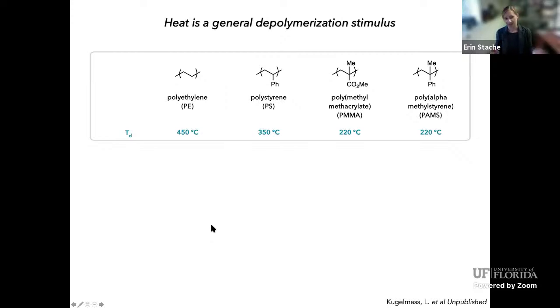Heat is a general depolymerization stimulus. And so we all know that polymers are susceptible to thermal degradation. When we think about thermal degradation, we think about kinetics, we think about thermodynamics. We look at some of our commodity polymers here: polyethylene, polystyrene, PMMA, and poly-alpha-methylstyrene, which we kind of use as a reference polymer in our lab. So kinetically, these polymers are all trapped when we make them. They don't have any reactive sites on the polymer backbone, and they all have specific degradation temperatures. So if you heat the polymer above this degradation temperature, you're going to start to break bonds in the backbone of the polymer and generate reactive species like radicals or ions that can then go on to do either cross-linking or depolymerize to give you back monomer. And so polyethylene has a much higher degradation temperature, pretty unsubstituted, and as you add substitution, the degradation temperature starts to go down.